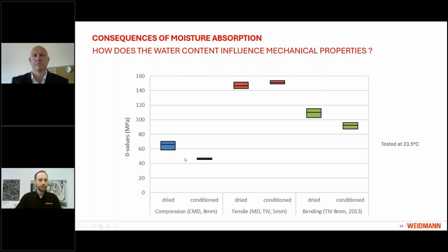And so when we have it dried, there is a high force needed to compress it compared to the conditioned one. The tensile properties are roughly the same, but here we can really see a difference in fracture image, because the conditioned one will really have more elongation, somewhere about 3.5, while the dried one is struggling to get to these values. And again, for the bending strength, we see that a dry material is much more forceful and has higher bending strength than the conditioned one due to the water it contains.